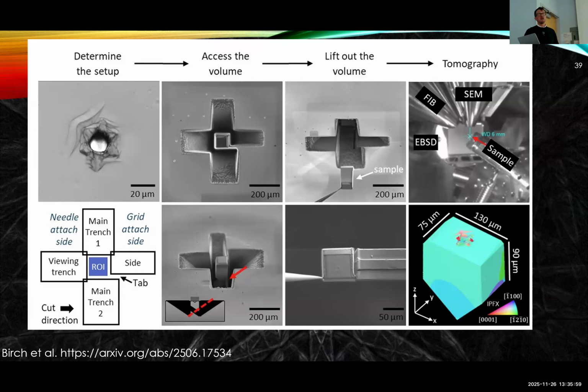We can also do site-specific lift out for this. So that was on the edge of a sample, which can restrict what you're doing. This is from Shuheng Li's work, working with Ruth and Warren Poole. Shuheng Li is interested in indentation in magnesium and local deformation. So here's an indent.